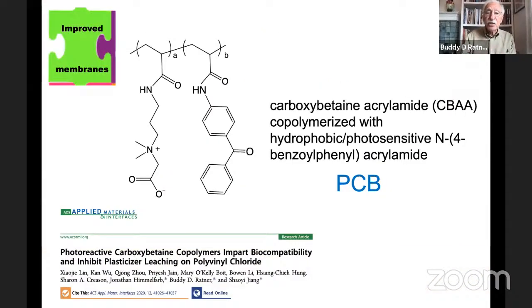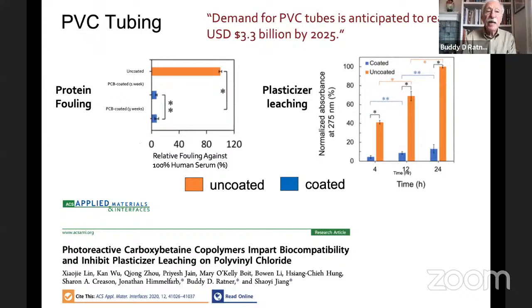So can we reduce plasticizer leaching? So there's the structure of a polymer we developed specifically to treat dialysis components. In that chemical structure on the left, you can see the plus minus of the zwitterionic structure, the carboxy betaine. On the right, there's a photoreactive group, a benzophenone type group that allows us to photoreact the zwitterionic polymer in a very facile manner with most materials and surfaces. And so we treated PVC tubing with this zwitterionic polymer. And here's just some of the data. I'll show you a little more later in this talk.